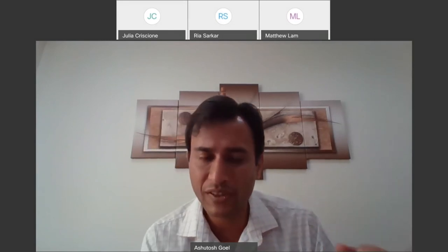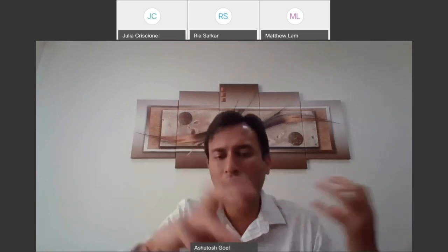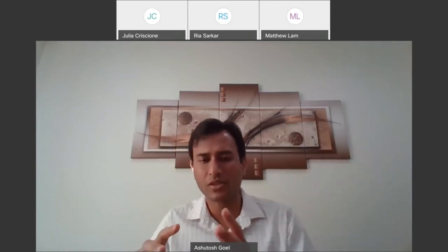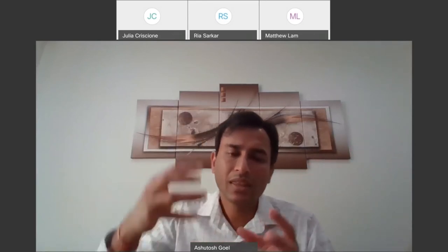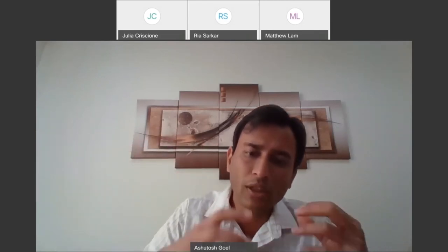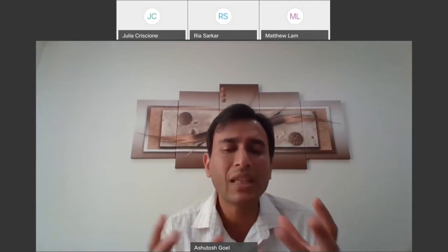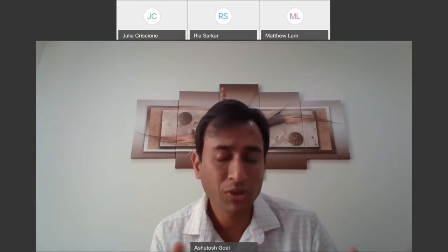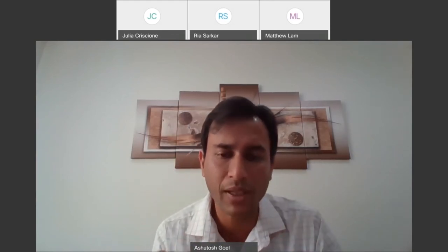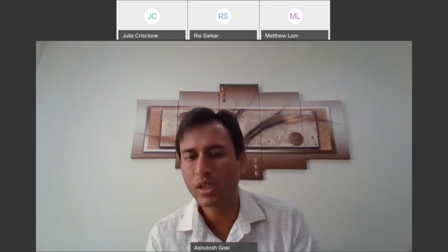Glass is amorphous in nature. In other words, the atoms in the glass are all randomly oriented, or they sit randomly in the structure. In a crystal, the atoms are periodic. They repeat the pattern. So in a ceramic, you do not have the flexibility to break that periodicity. Because it's a crystalline material, you have to have that periodicity. Otherwise, the ceramic structure will break down at the atomic level. And then you won't be able to hold the nuclear waste in it.